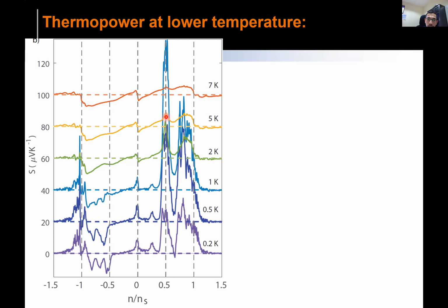If I decrease further, at 5 Kelvin, the peak is even increasing, and at 2 Kelvin even more. 1 Kelvin is dramatic. You know, it's quite large around that point. So not only at 2 electrons per filling, even at 1 electron per filling, the peaks are appearing. Even the 3 electron filling, although it's not very clean, is also appearing. Further, if I lower it down, although the electron side is not exactly like the hole side, you see a response even at the Dirac point. Very, very fascinating. At that point also, you see a single thermopower peak.